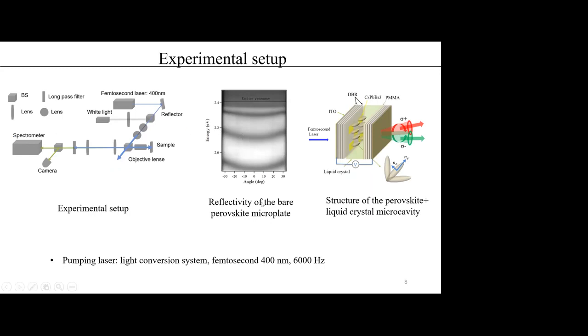We firstly measure the reflectivity of one bare perovskite microplate, and we can get a similar dispersion as the Savvidis group, which shows clear strong coupling in the perovskite microplates. The thickness of this selected perovskite microplate is around 200 nanometers, so we do not observe the anisotropy of the perovskite itself. To fabricate the liquid crystal microcavity, firstly, we transfer the perovskite microplates onto the bottom DBR and paste the top DBR to form the empty microcavity. Finally, the liquid crystal molecules are filled into the cavity, where the molecular orientation can be controlled by the external voltage, which is applied onto the surface of the DBRs.